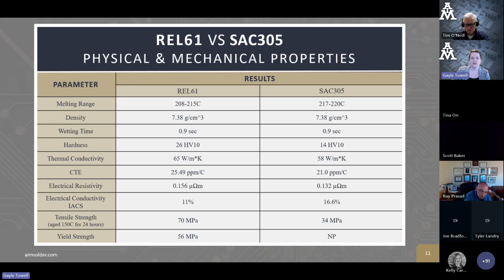All right, so here's just a direct comparison of some of the physical and mechanical properties of REL61 with SAC305. You can see melting range, it's melting about 5 to 10 degrees cooler in Celsius. Density is pretty much the same. Wetting performance is fairly similar. It has improved hardness. And then the other really interesting one is the tensile strength after aging. We have some pictures of this later in the presentation, but when these alloys were cast and then aged at 150 Celsius for 24 hours, we see REL61's strength pretty much stays the same, but SAC305 and a lot of other alloys, their performance goes downhill very fast. And so that's a very big distinction between REL61 and many of the SAC alloys.